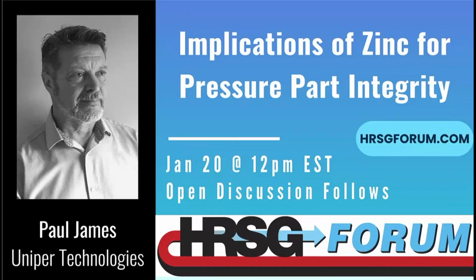I mean, certainly you read through the literature, and there's some reference there that even when you grind it away, there might still be some residual, but I would say that's going to be very minor amounts, and it's not a stainless steel. I think that's the key thing. Stainless steels are clearly vulnerable to liquid metal embrittlement, and a couple of examples were shown on that. What we're dealing with, the grade 91, looks to be zinc diffusion. So you're going to be looking at a quite discrete zone. What we've seen on the examples in the UK, and it's probably been repeated elsewhere, is essentially this dark ring around the weld. It basically follows the heat affected zone around the circumference, and as such, you potentially have a ring of weakness there, notwithstanding that the flank position is more highly stressed and more vulnerable to sustaining